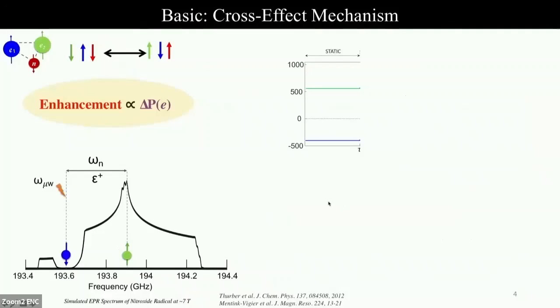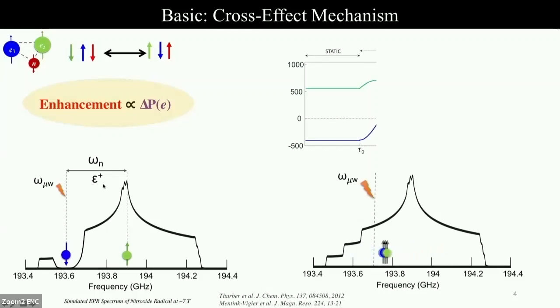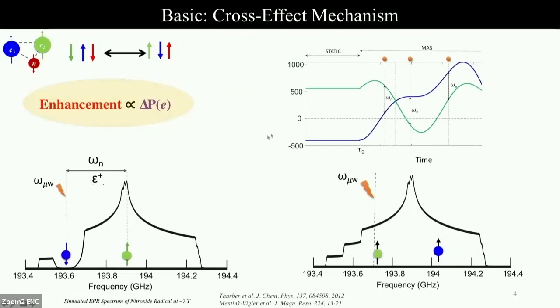The most important thing about cross effect is that we need to generate a large polarization difference between the two electrons. This is the crux of cross effect mechanism. Under MAS, things are a bit more complicated because the electrons' energy levels are modulating because of rotation. But here too, the crux is whenever we have this cross effect resonance satisfied, we should have a large polarization difference between the two electrons.